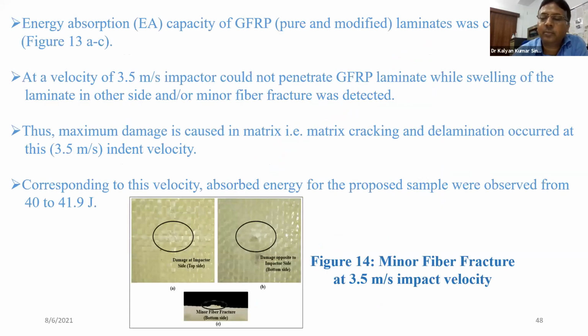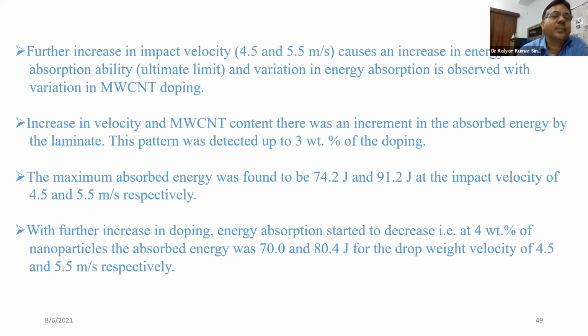Now look at this: minor fiber fracture at 3.5. See what was found with our earlier research. I told you I have been 20 years in composites. See the research from the initial 10 years. We have to find out the impacted area, calculate that area, and say that this much area is damaged. By knowing all these different weight percentages, the maximum absorbed energy was found to be 74.2 joule and 91.2 joule at the impact velocities of 4.5 and 5.5 meter per second respectively.